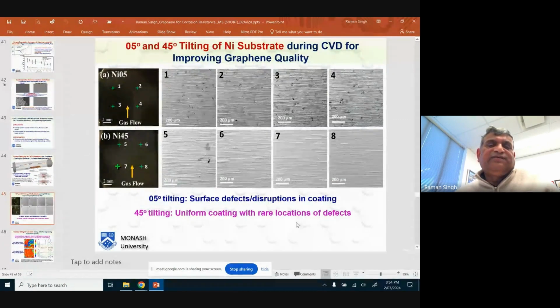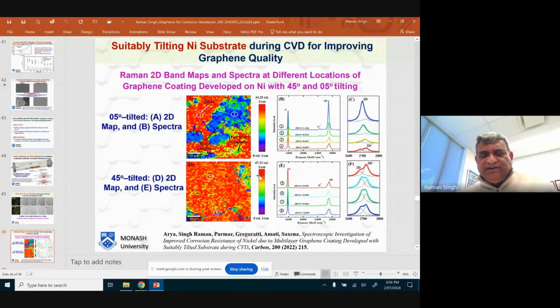You can see that 5-degree tilting had graphene with lots of defects. You can see very clearly in the SEM images. Whereas the 45-degree tilted one has very little discontinuity. The graphene quality was very good. This aspect of the work is about to go for publication to another journal.